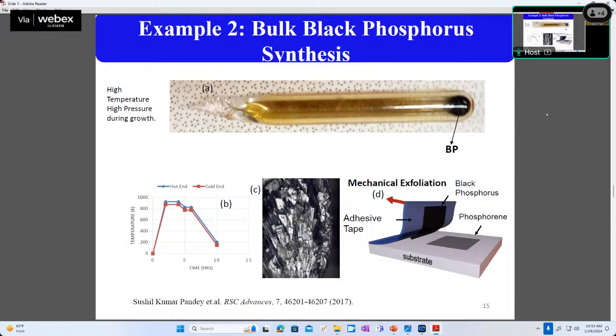At high pressure, the systems we have cannot operate. So there is a special way to grow this, called the chemical vapor transport technique. We have used that, and this material basically requires this condition, and we were able to grow this material. That is called black phosphorus. So crystals look like this.